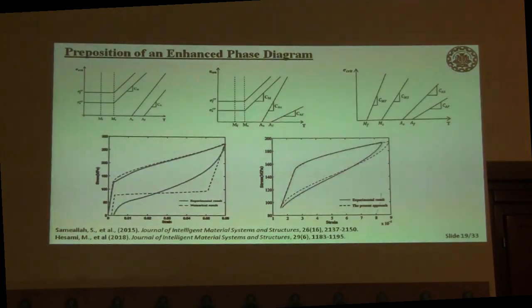In our observations, we realize that we should think about generalizing this typical phase diagram, at least by changing the considered slopes of this strip, or for example for both strips. You can see the response. If I wish to use the typical phase diagram, I cannot easily resemble the experimentally verified response. The dashed lines are numerical simulations using the ordinary phase diagram. But if I use these generalized phase diagrams, I can obtain a more reliable response.